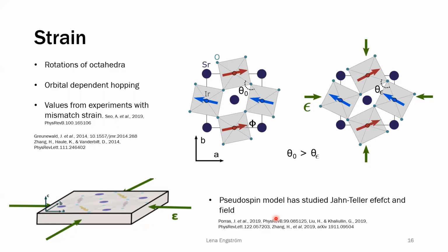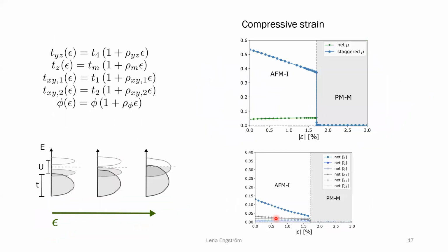The effect that this has is that it does change the hopping between different sites, but due to us having these orbitals that are oriented in different directions, it means that it does change the hopping between orbitals in different ways depending on which orbital we are considering. So to see the effects that we get, we linearize the effect the strain has on all of these hopping parameters that we were considering before.